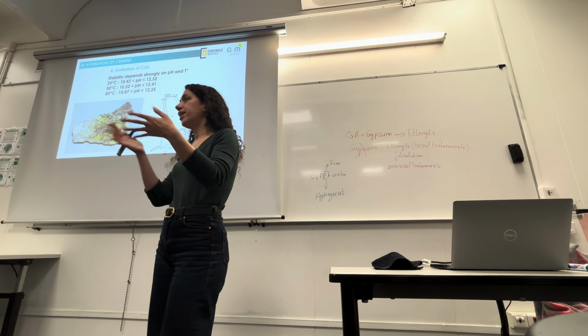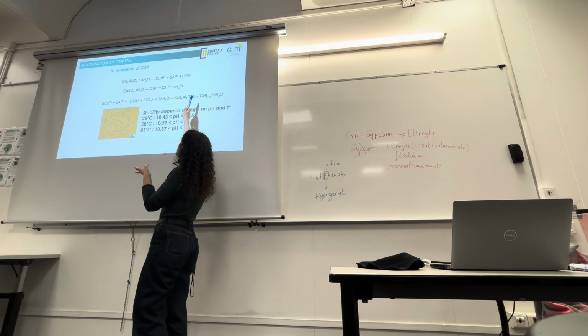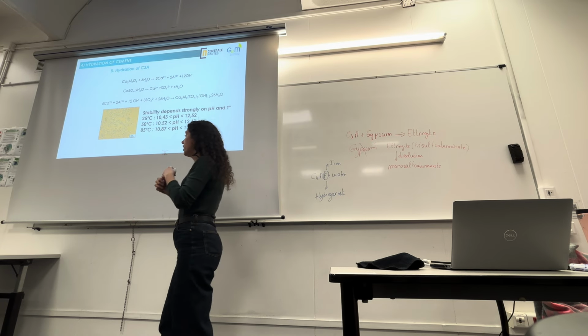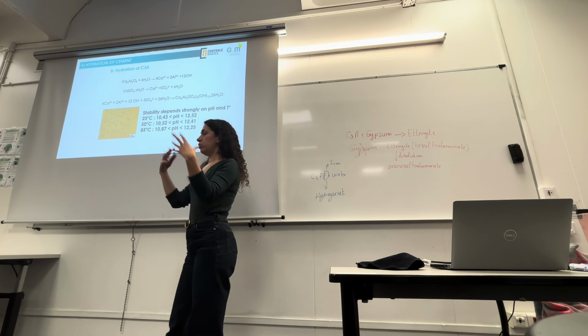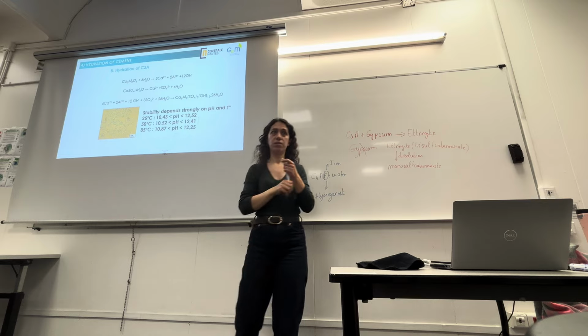And can you go back on the slide? You said that this dissolves and precipitates, and then something. This one? Yes, this one. So this one is mostly the dissolution. The first two equations are the dissolution equations: dissolution of C3A, the first one, and the second one is the dissolution of calcium sulfate. The dissolution of calcium sulfate and C3A release different ions into water: calcium, aluminate, hydroxide, and sulfate. They are all in water, these ions, and they react all together to form ettringite.